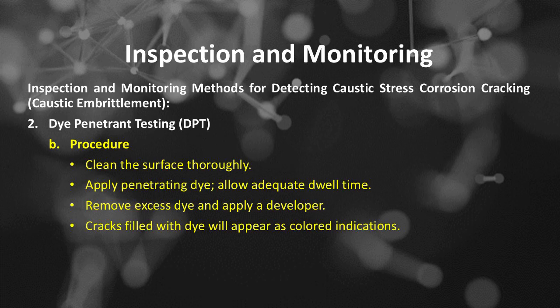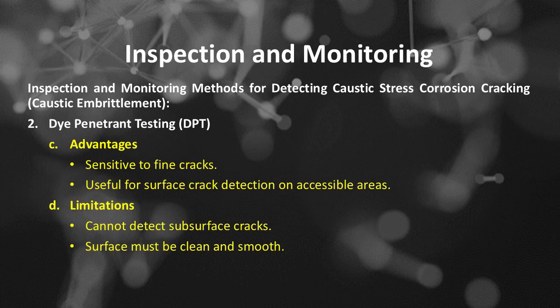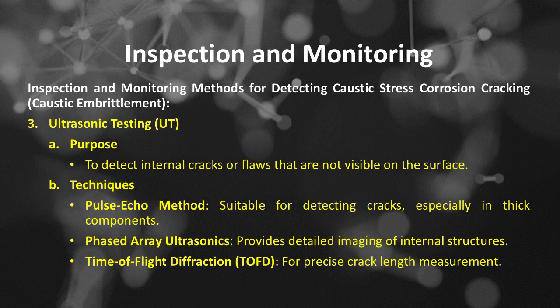Cracks filled with dye will appear as colored indications. The advantages of dye penetrant testing are sensitive to fine cracks and useful for surface crack detection on accessible areas, and the limitations of dye penetrant testing are, it cannot detect subsurface cracks, and the surface to be inspected must be clean and smooth. Inspection and monitoring methods for detecting caustic embrittlement.